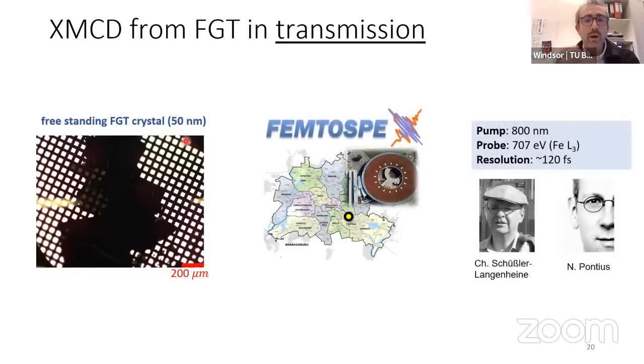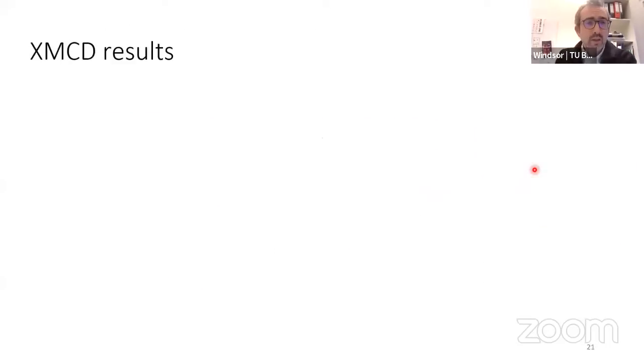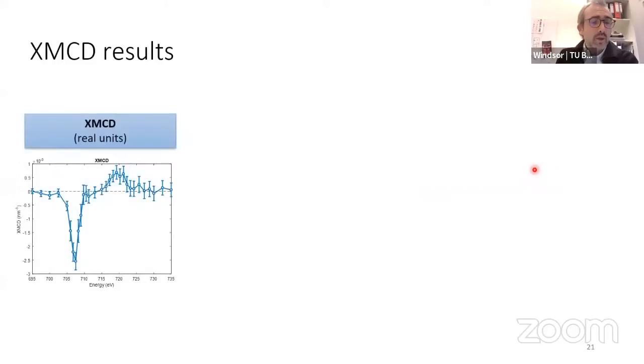We went to FemtoSpex, which is an ultrafast beamline at BESSY II, and worked together with our colleagues there to probe the system. So this is what the data initially looks like. This is our XMCD spectrum from FGT. You can see that there's a difference here between left and right circular light, and we get the L2 and the L3 peaks as we would expect.